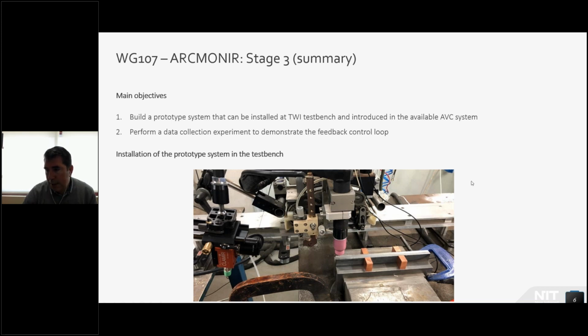In the photo, you can see the installation of the prototype. Now we have the infrared camera, the image processing electronics, and the control electronics, everything embedded in the same camera. And this is the system that will look at the process area. In this case, you can see the sample with the 2 copper heat sinks, and it will perform the closed loop control of the arc voltage. The idea is to keep the melt pool width constant during the complete process, which will increase the quality of the process.